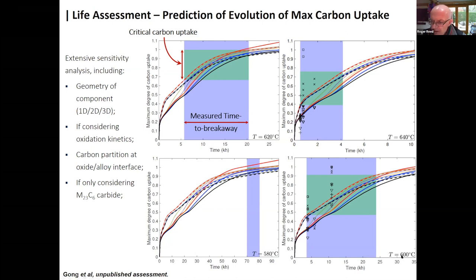You can see particularly at 600, 620 and 640 degrees Celsius, the data points, I should say, give you an inkling and an idea about the scatter in the data available to EDF Energy. And of course, one has to interpolate through this. But as I say, the basic idea is to come up with an estimate of whether the reactor is safe based upon the available reservoir of metal available to further take up carbon in these systems.